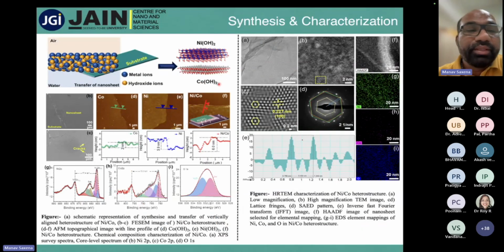So here you can see in figure B the nanosheet, and we have studied this vertical heterostructure by AFM analysis, and we can find the complete thickness of the film at the edge. We can see the sharp edges are around 6 nanometer, and we have done the XPS study, which shows that cobalt and nickel are both in +2 oxidation state, and there is some trapped water between the layers, because however we dry it, we cannot completely remove the water between the substrate and the layer, and in between the layers. So there is some amount of water also present.